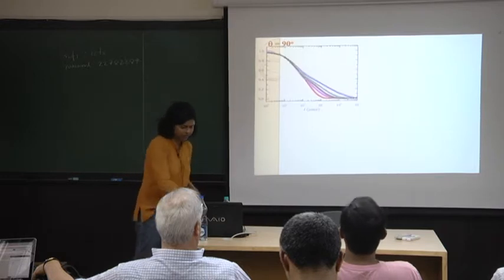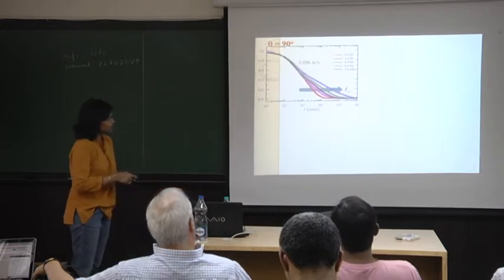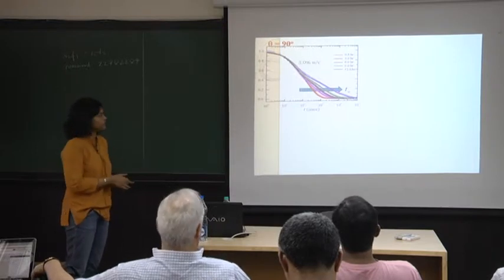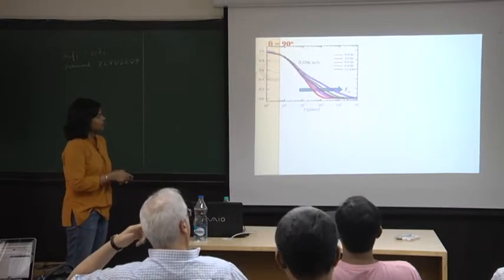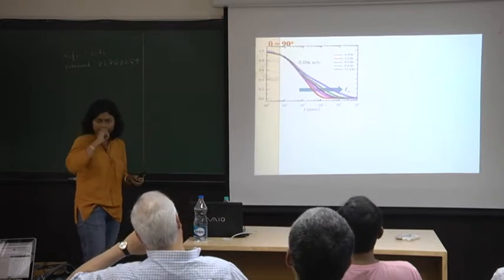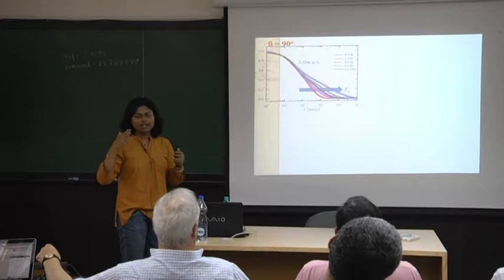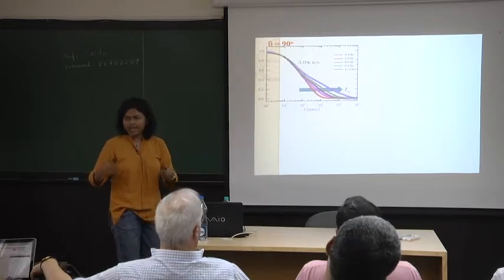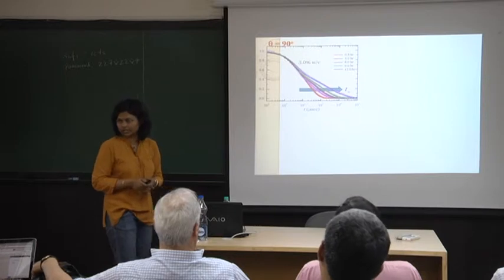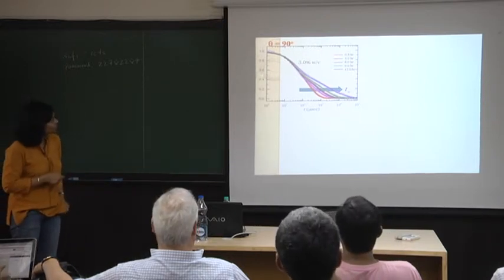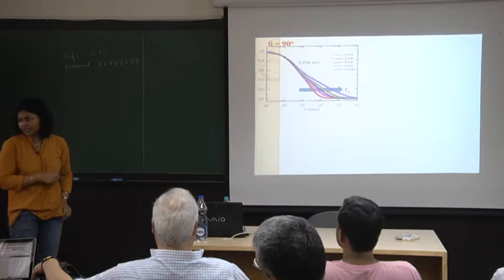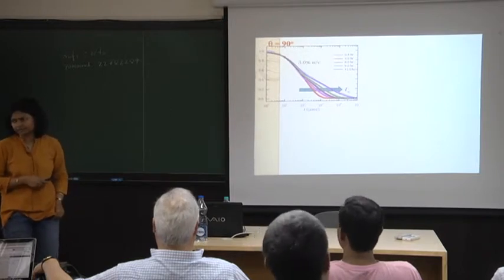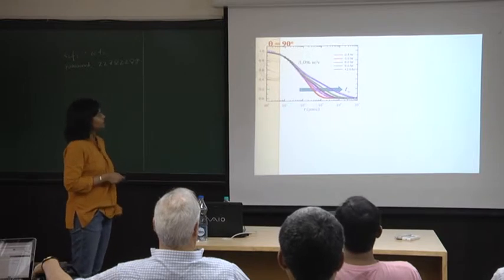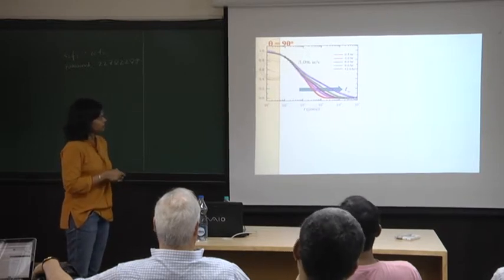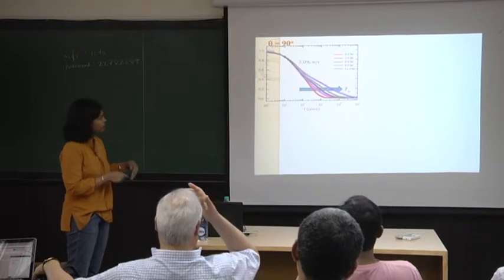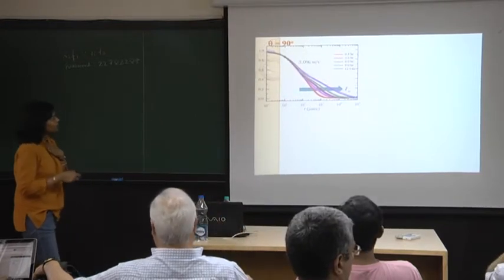These are the correlation functions for aging clays. So this direction is the direction in which the samples are older and older. You fill your little vial, you put it in your rig, you send laser, and you just wait for it to spontaneously evolve, and every now and then you are making an intensity autocorrelation. Oh, I'm sorry, this is really the amplitude correlation function. So this is basically the suspensions getting more and more aged. So these are older samples this way.